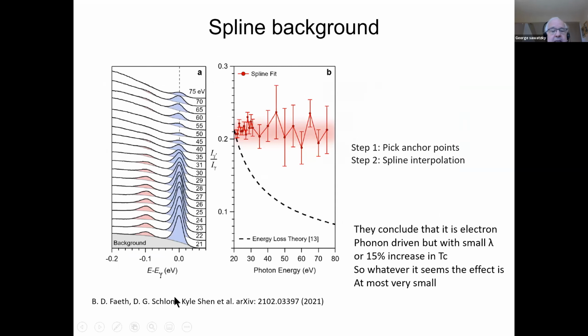But here's a paper that just recently came out with D.G. Schlom and Kyle Shen and so on. These are good people, and these are very reliable and very nice experimental results indeed. But again, you have this large background that these things are sitting on. And what they did is they used a kind of spline method. So they just pinned the points in between the two peaks, the blue one and the red shaded one, pinned the background there and on the other side over here and a few other places, and did that all the way through.